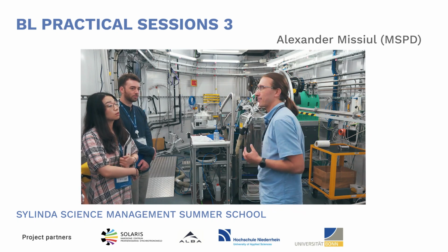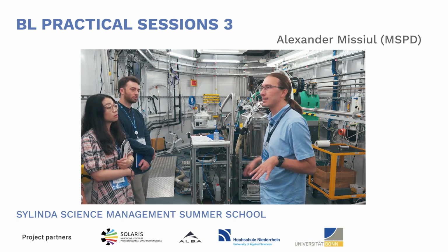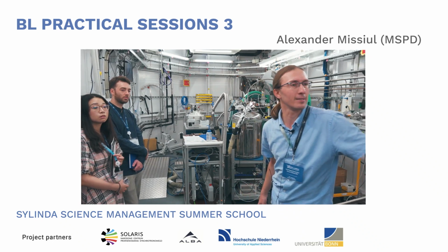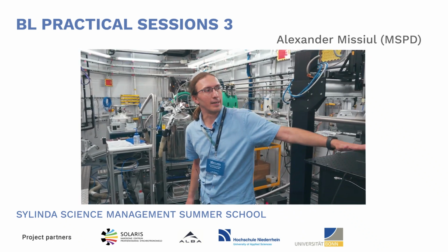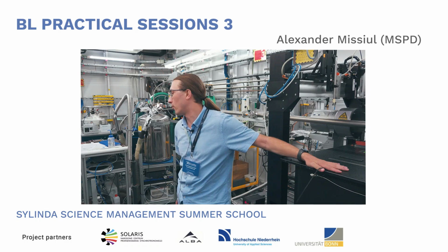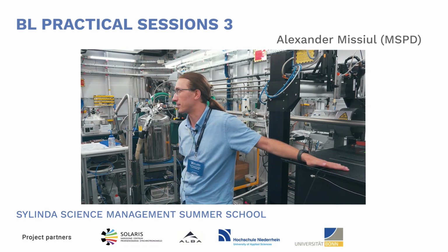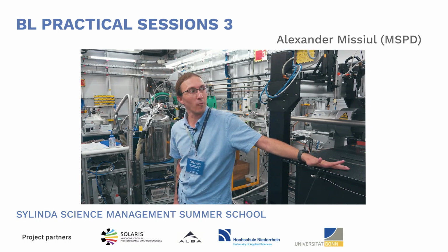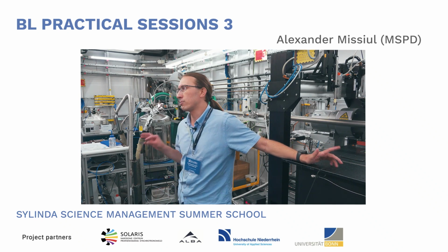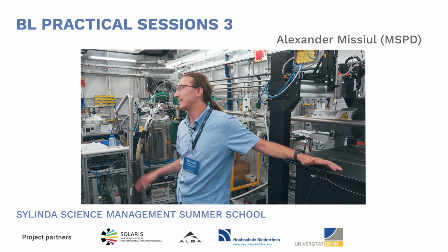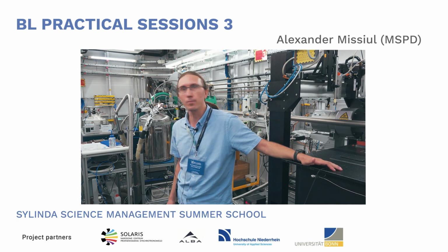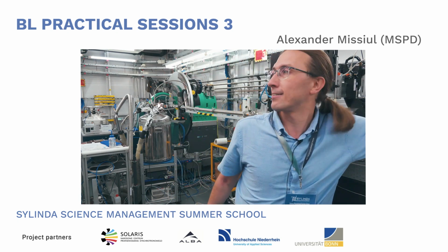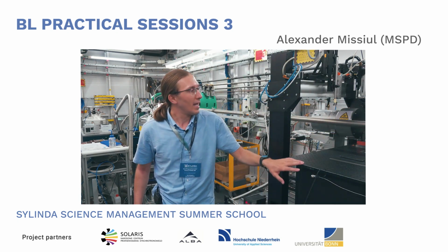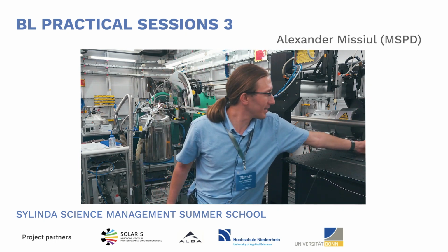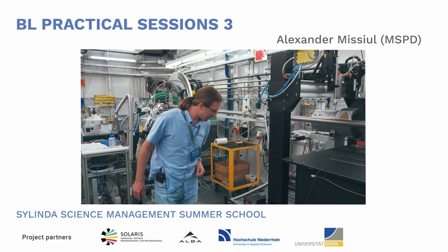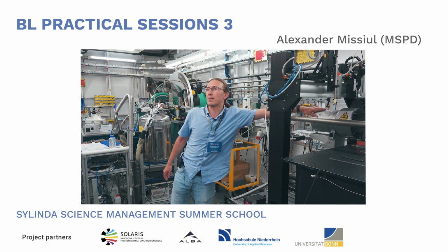To do this, we have two experimental stations here. One, which we see here on the right from you, is the station for high pressure and micro diffraction experiments. Here we focus the beam down to 15 to 20 micrometers in size. We have a focusing mirror here inside this box. And so we put the sample here and measure it, collecting the data using the two-dimensional detector.